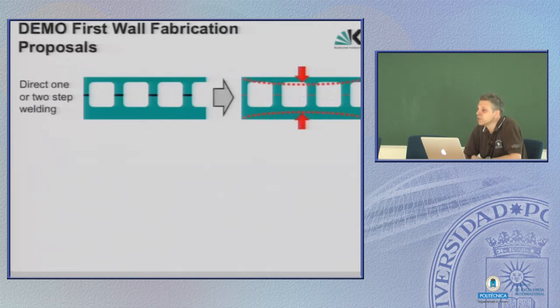However, due to the pressure and the high temperature you need for diffusion welding, temperatures are around 1000 C or even higher. And remember what happens at high temperature and pressure. Material creeps, and this is exactly what happens during the welding process. Due to the pressure, the plate bends from both sides, and this is at least a small drawback, because we want to have the plate straight, but afterwards you have to take into account that they are bent more or less, depending on pressure and temperature.